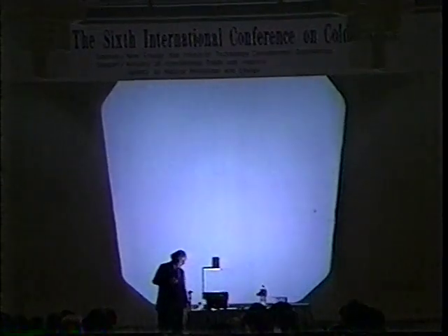So instead of that, we use another procedure which was used, I mean, this is exactly the same, the replication of Fleischmann and Pons' experiment. We measure the amount of water lost during boiling. What's interesting here, you're working at constant temperature, almost constant temperature. And the excess heat now is the enthalpy used for vaporization of the whole content of the water.